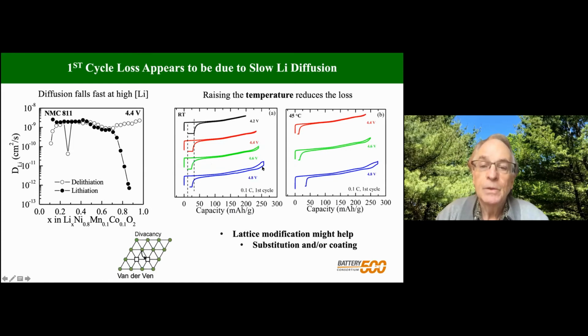But as we go to extremely high voltages, we're getting a number of side reactions and obviously damaging the surface of the material, if not the bulk. We're getting much more polarization. If we increase the temperature from about 21 to 45 degrees centigrade at 4.4 volts, you can see we've eliminated almost all the first cycle loss. It's again indicating that this is a diffusion controlled reaction.